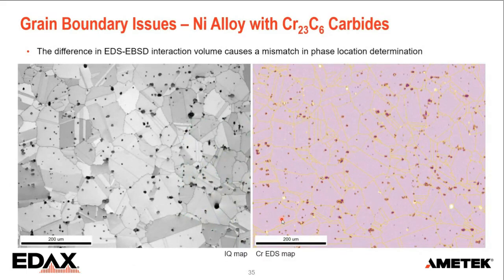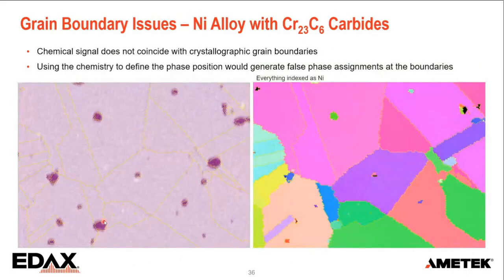Here, I really like to illustrate that with a nickel alloy with a carbide. The interaction volume for EDS is much larger than for EBSD. So that means that the signal coming from those small particles is bigger than the particles themselves. If I zoom in here on the right, you see a chromium map where I just highlighted all the boundaries. And when I zoom into that, you can see that the chemical information is larger than the grain.